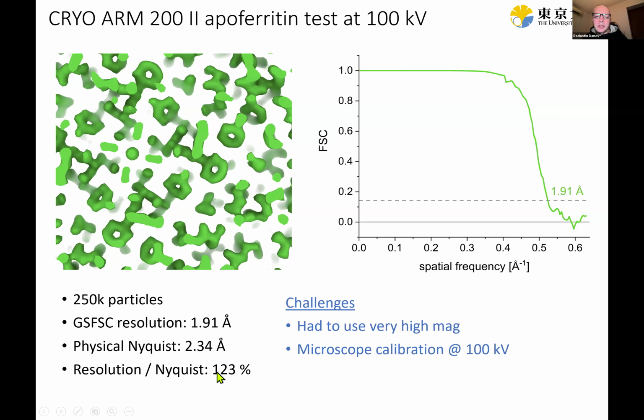The practical challenges: one that I mentioned already is using very high magnification, which was very unusual, and calibrating the microscope at this magnification was also not very easy. It was not fully calibrated, but already the time for the loan was coming close to the end. So anyway, it was not an optimal setting. There may have been some ways to improve it further, I guess, if we had more time.